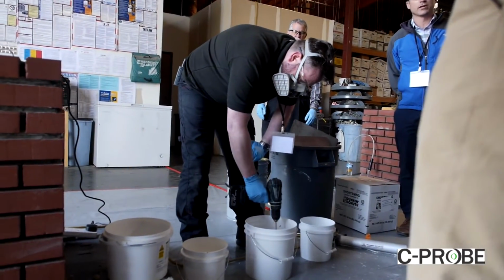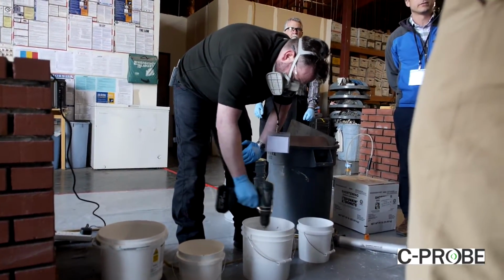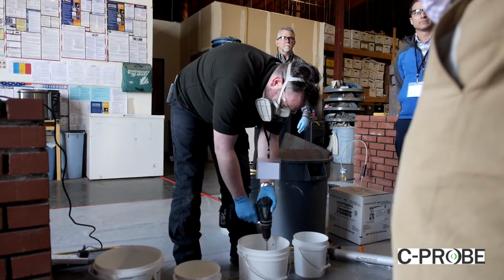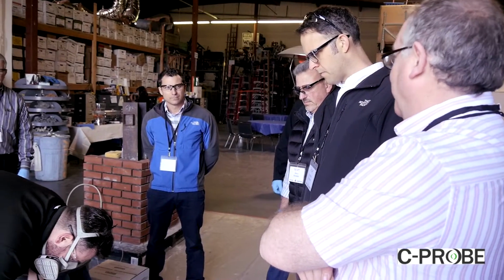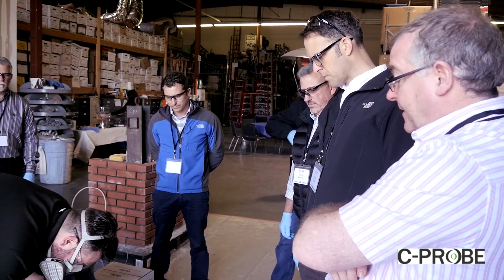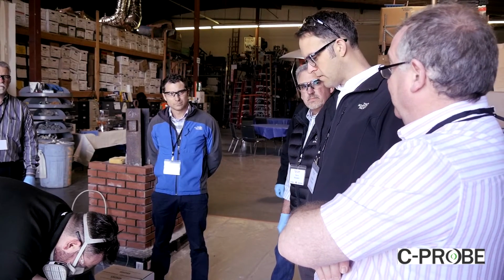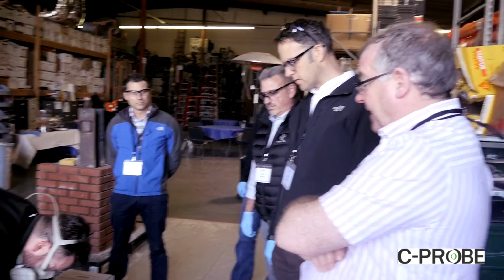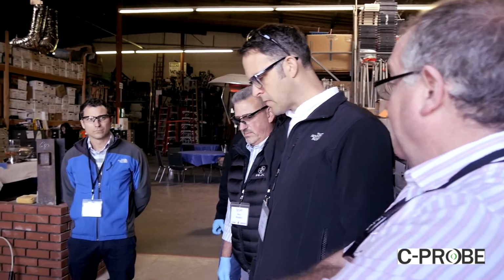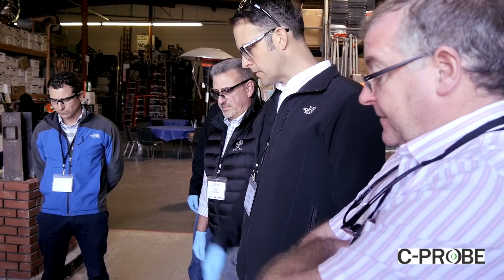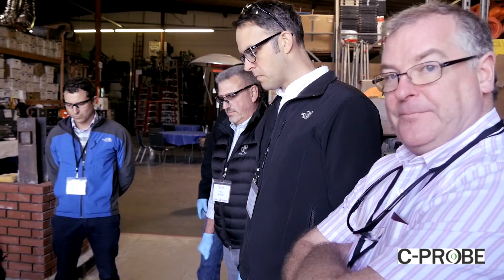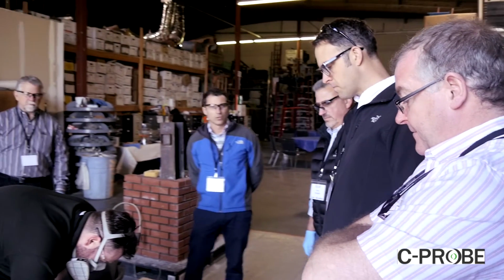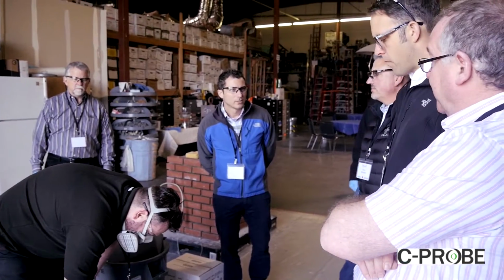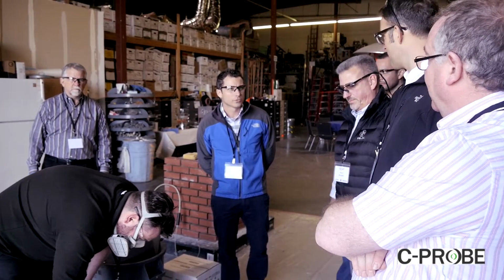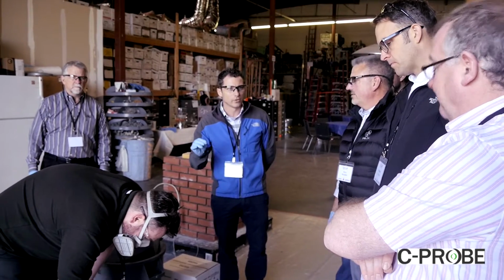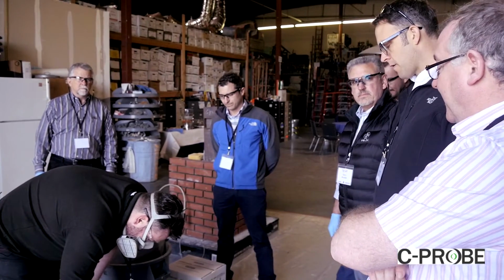So adding colour, like a coloured aggregate, doesn't affect its performance at all? Nope. We add any sort of aggregate, and the compressive strength is measured on cubes normally. But typically in the concrete we're finding 50-60 megapascal. Here we've got a little less of the silicate solution in, so we're down to about 20 megapascal. It's softer. Could you adjust the compressive strength if you wanted to? You can tailor it according to what components you put in the mix. Say you're pointing back to terracotta, a really soft material. It's very important that you want to reduce it, even down to less than 20.